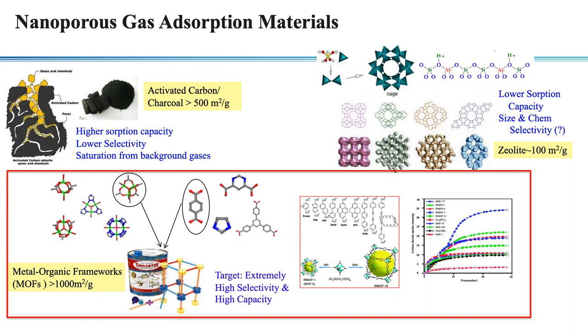What I'll primarily focus on today are metal organic frameworks. These are a combination of both carbons and zeolites — highly crystalline materials that combine metal nodes, which are sort of the corners, and ligands or organic parts, which are the connectors. Thinking of a tinker toy setup helps. How you choose the metals and linkers enables high design of different porosity and chemical functionality. As an example, work from Omar Yaghi's group shows that using the same metal center but extending the linkers greatly extends the surface area inside the pore, changing adsorption capacity and selectivity.